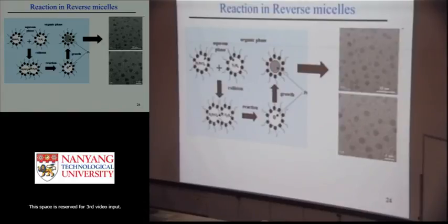So how do we do it? Typically, we make one microemulsion containing the platinum chloride dissolved into the water droplet. Make another beaker of microemulsion, allowing hydrazine to be dissolved into the water droplet. Then you pour them together. You will see collisions between the droplets form dimers. Then the hydrazine meets the platinum chloride and makes platinum 4+ become platinum 0. Then nucleation starts, followed by growth. Finally, you have the nanoparticle.